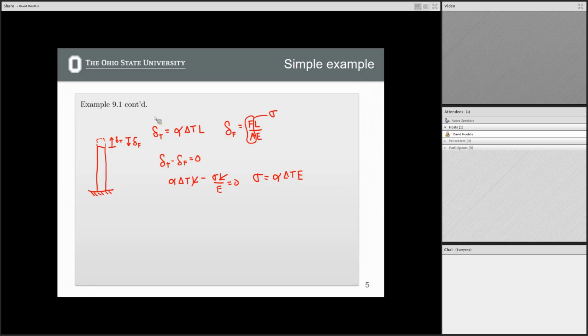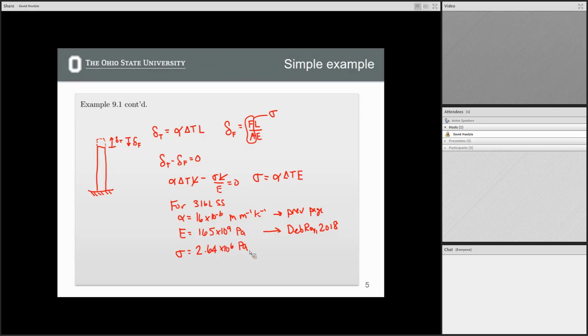So for 316L stainless steel, alpha is equal to 16 times 10 to the negative 6. Young's modulus, 165 gigapascals. That's 10 to the 9 pascals. This is from the source on the previous page, and this is actually in that survey article, the Debroy 2018. All right, so then we can now find a relationship for stress as a function of a change in temperature. Oops, forgot delta T.